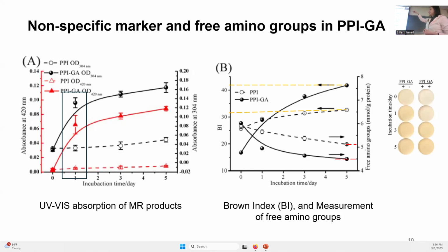If we look at the black lines, that's the absorption at 304, and the red lines are the absorption at 420. After the first day of incubation, we see an increase in both absorptions, which was attributed to the increase of browning and Maillard products. In the second graph, they're showing the browning index on the left Y axis. We can see that it increased after 5 days of incubation, but after 1 day it is the same browning index for both incubated and not incubated. But when we look at color, we do see a little difference. The first column here is just the pea protein, and the second column is pea protein with gum arabic and different types of incubation.